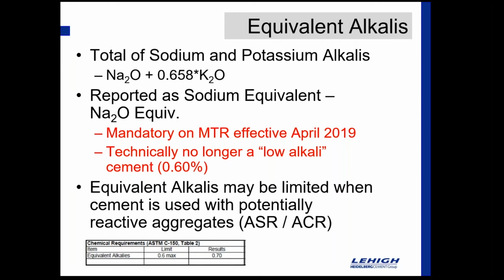But with the C1778 guide for reducing the risk of alkali aggregate reaction in concrete, the alkali loading of the entire concrete mix is really now what's considered when selecting the mix components. I don't think people that make a low alkali cement are going to stop making a low alkali cement, in my opinion, because that cement contribution to the overall alkali loading of the concrete is very significant. So I think if there was a need for it before, that need's still going to be there. It's just technically they no longer specify or call out that low alkali cement.